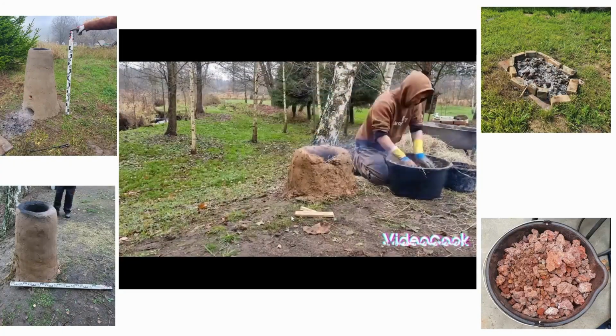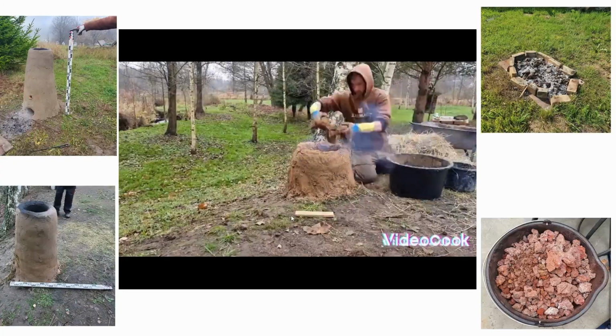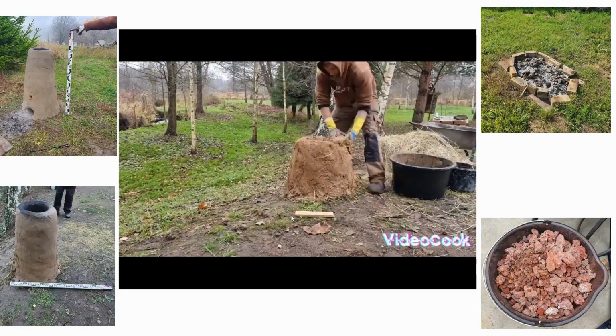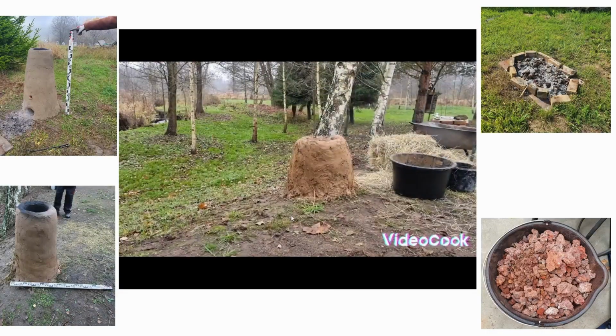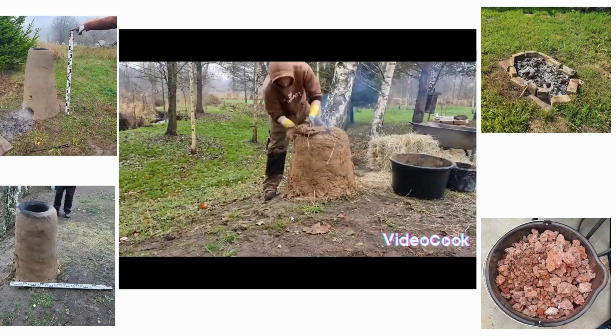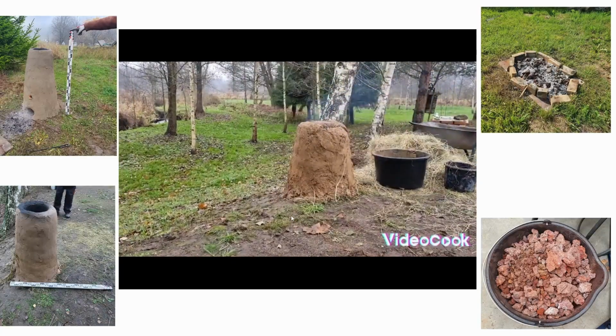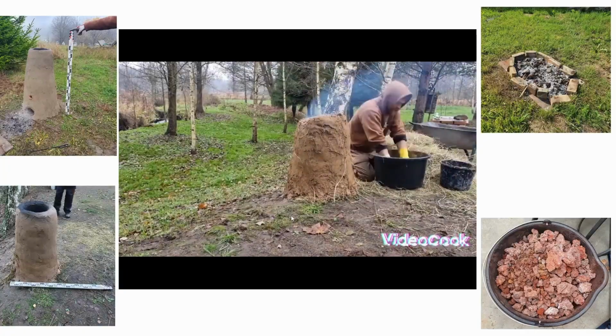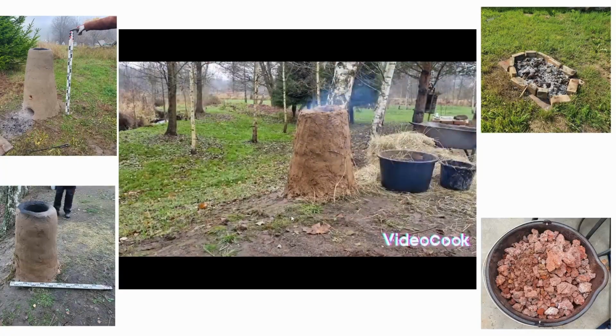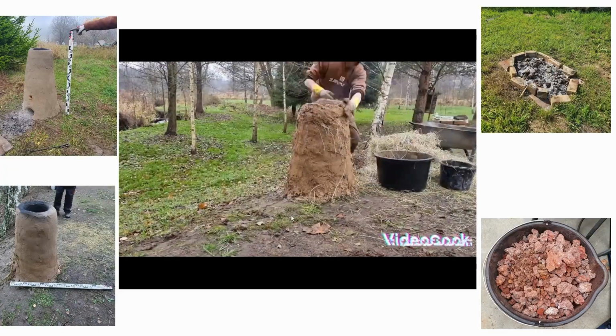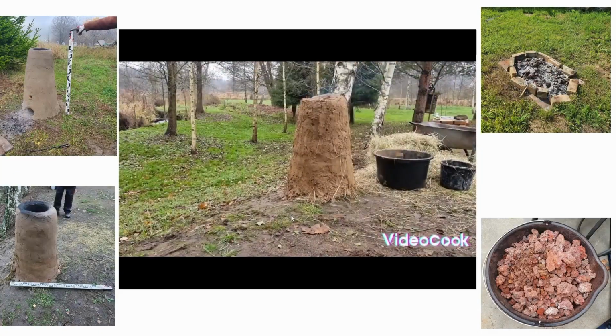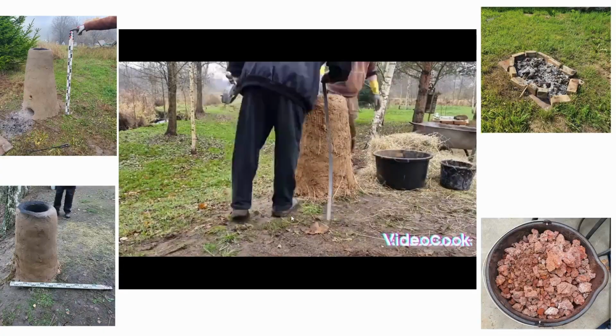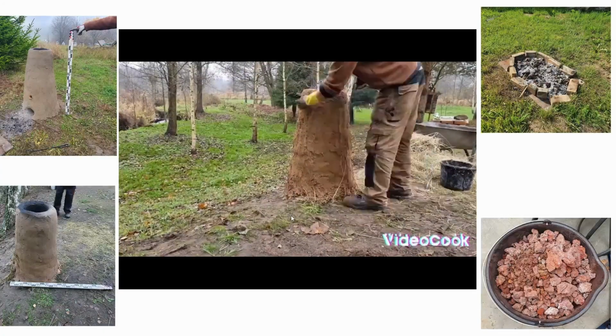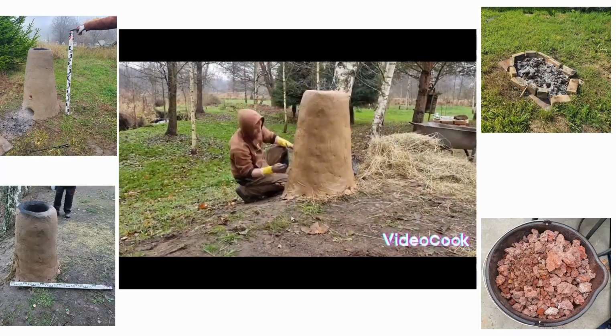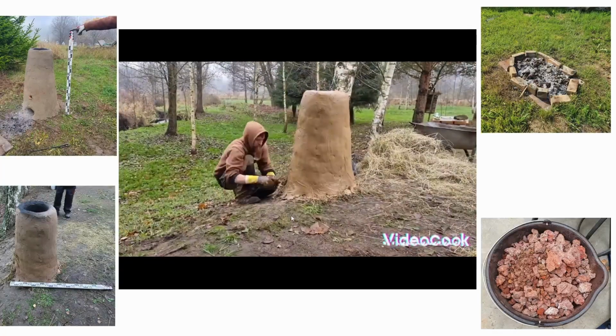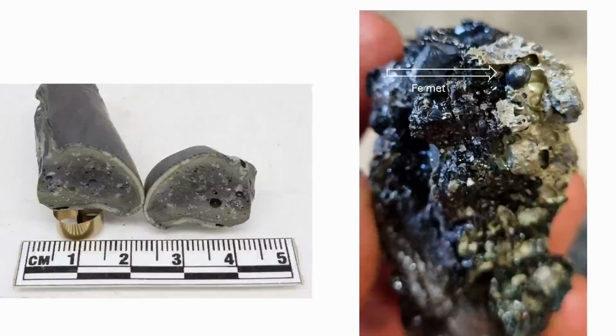During the initial experiments with tapping furnaces, the tapping slag was very viscous. No fayalite or wustite, typical of archaeological slags, was detected, suggesting that some iron remained in its trivalent form due to inadequate reducing conditions. Fayalite requires divalent iron, which was lacking, resulting in predominantly glassy and greenish slag.